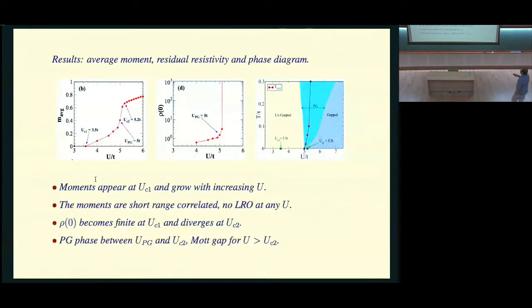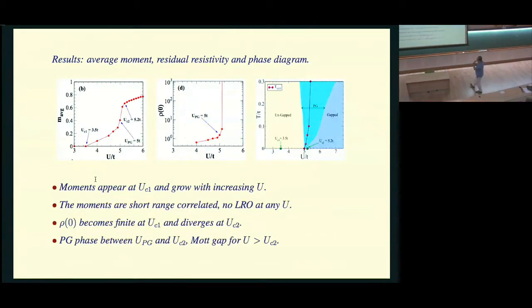This is the finite temperature variant of this, showing that there is a UC1 at which moments form. Then a metal, if you believe this, a pseudo gap phase, and then an insulator at UC2. There are no finite temperature transitions in this problem. Had I been doing it for the cubic lattice, for example, there would have been a line defining the antiferro insulator versus the para-insulator or parametal. So, finite resistivity at zero temperature. In fact, this is the first instance within this calculation of spontaneous disorder emerging due to frustration, if you wish.